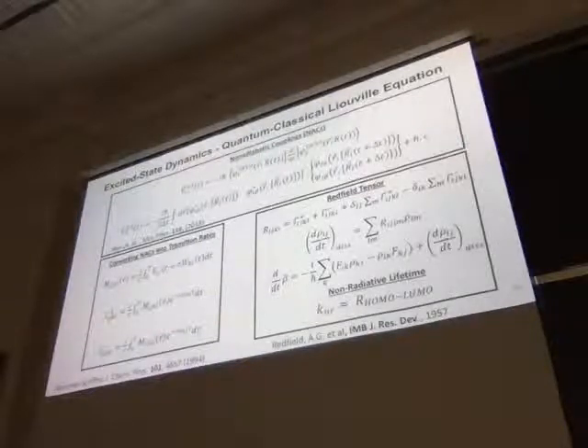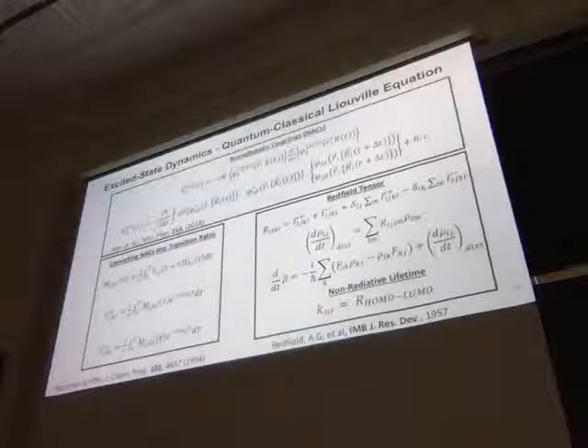And so this is just a direct notation. This term here is showing that we're using spinors, non-adiabatic couplings, and just to emphasize that the updated time step for one orbital is compared to the previous orbital. Whatever overlap they have is proportional to the transition rate between those two orbitals due to the heat. This is the most computationally demanding aspect of the model that we do. It was first developed in the group in 2018, and since perovskites require the spinor orbital formulation, we've applied it to model perovskite systems. And that's the novelty behind this.